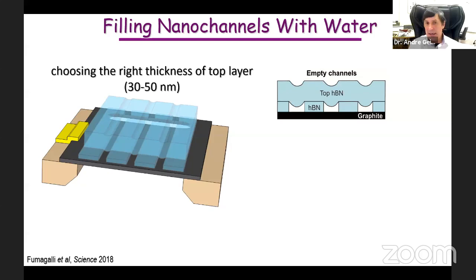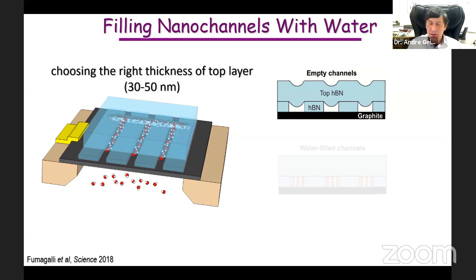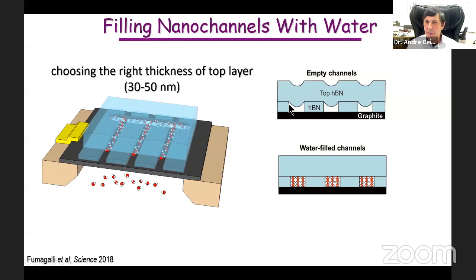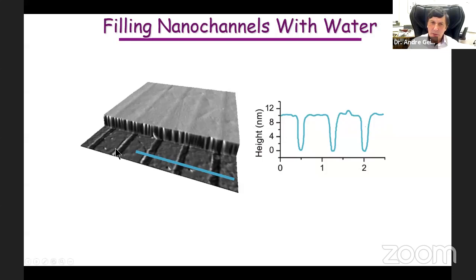So when we add water inside, what's happening is that as water intercalates or goes inside, it reduces this interaction with the side walls. And in this case, what we observe experimentally is that the top crystals become flat. So we use this as an indicator that water is indeed inside the channels. So this is how we do our experiments.